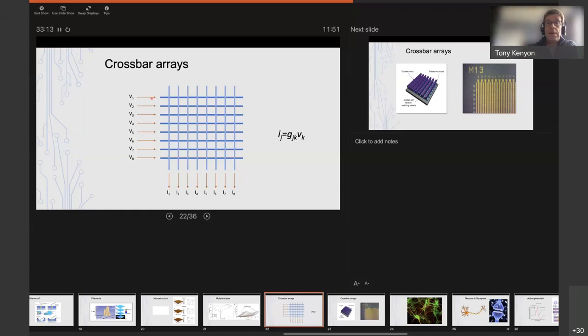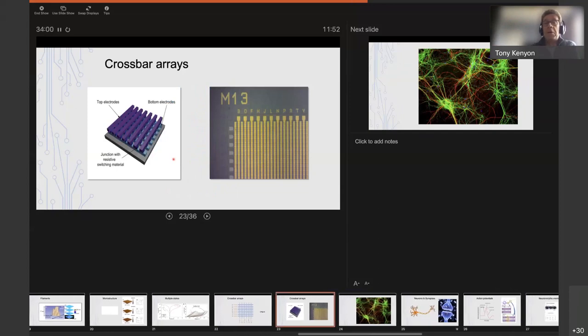So as your array gets bigger, as the size of this matrix scales, then the energy cost, the time cost, the complexity of that operation scales roughly as the square of the size of the matrix. In this case, however, if we just simply apply voltages and read currents, Ohm's law here, just conductance times voltage gives you the current, does everything for you in a single shot. So in fact, the scaling, well, there isn't any scaling. So once you've written your matrix values into this matrix, it doesn't matter how big the matrix is, you get your answer in one shot. So this saves you a huge amount of time, energy, power.